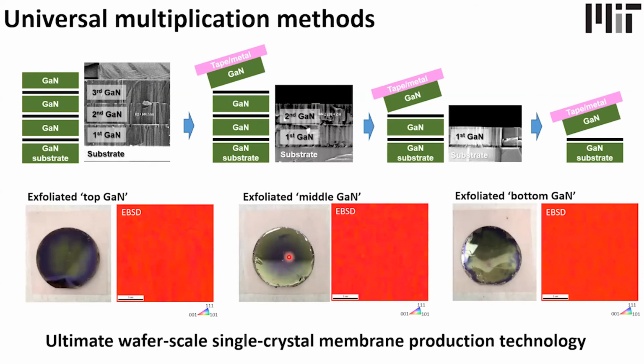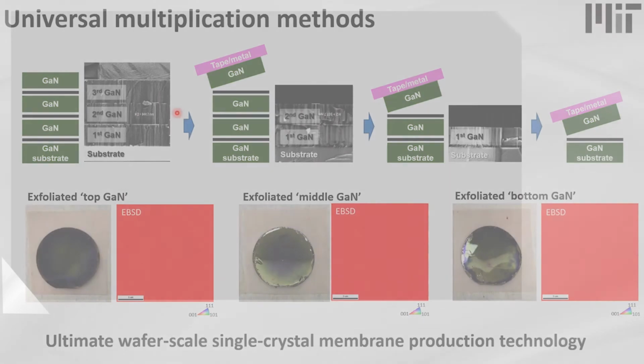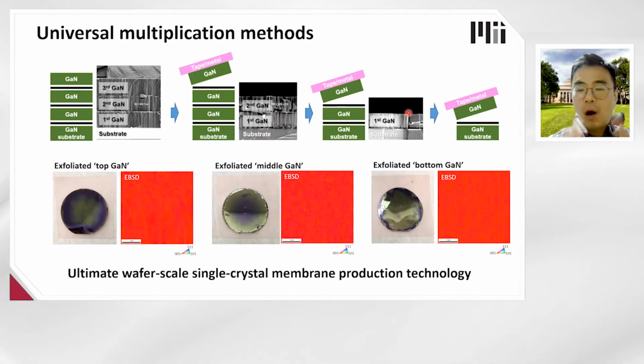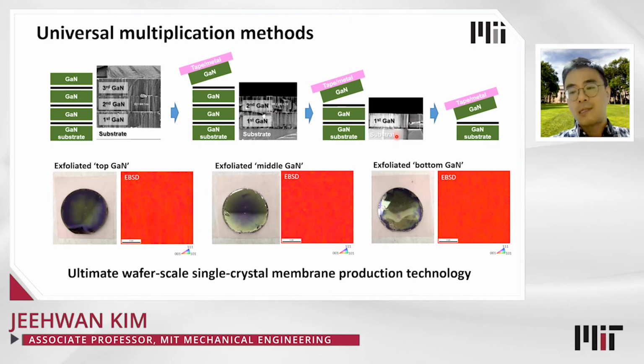Okay. Also, we further reduce the cost of producing the freestanding membrane by inventing the multiplication method. The way it works is as follows. We have a compound material substrate, and we grow monolayer 2D material in the MOCVD chamber. We grow 2D material, then 3D compound material, and we alternate 2D material and 3D material many times in a cycle. Then by performing only one single epitaxial growth run, we are able to produce this stack, and we are able to harvest the single crystal material from the top one by one, as you can see here. That way, you can really reduce the cost of this kind of expensive single crystalline material.